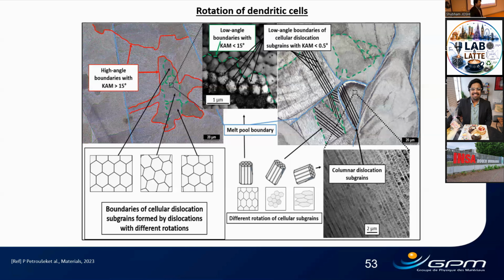Just one last question on the grain size and texture effect. There are some works in the literature where people have been doing synchrotron or neutron diffraction analysis, looking at the effect of the grain morphology on the local stress and comparing to numerical simulations. And when you do that, it seems that the grain morphology has no significant impact on the mean stress, on the stress at the grain level, for some reason which is still unclear to me. But they are more or less in that direction, and that could also be a way of analyzing the local stress more precisely.